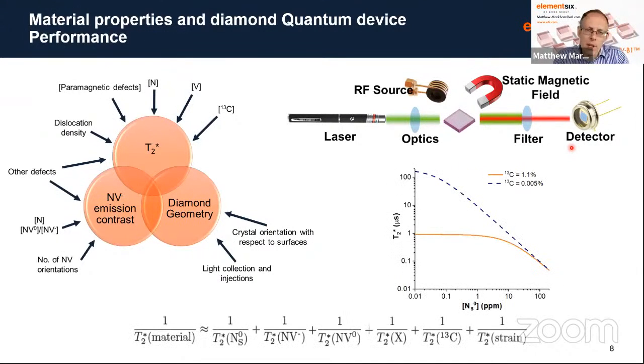So when it comes to probably one of the most important parameters, which is T2 star, there are lots of contributing factors that affect T2 star. So obviously any residual nitrogen in the material can have dipole coupling to the NV defects and therefore affect the spin lifetime.